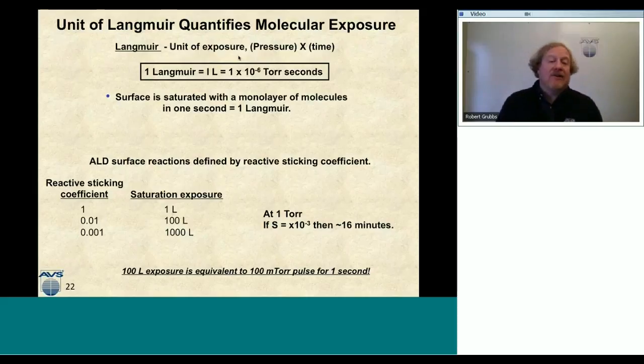But ALD surfaces are really defined by their reactive sticking coefficient. This is all assumed with a sticking coefficient of 1, but that's rarely the case in ALD. So here's a reactive sticking coefficient of 0.01. Now I'm going to need 100 Langmuirs of material before I reach surface saturation. And if the sticking coefficient is 0.001, then I'm going to need 1,000 Langmuirs of exposure in order to reach that same monolayer coverage.